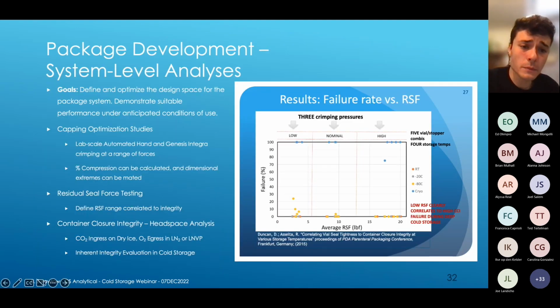The last part of a capping optimization study would be, of course, to implement and integrate container closure integrity testing. In this case, we're talking about headspace analysis using either CO2 ingress on dry ice, oxygen ingress during liquid nitrogen or liquid nitrogen vapor phase storage, and then Lighthouse headspace analyzers to measure change in headspace concentration over time.